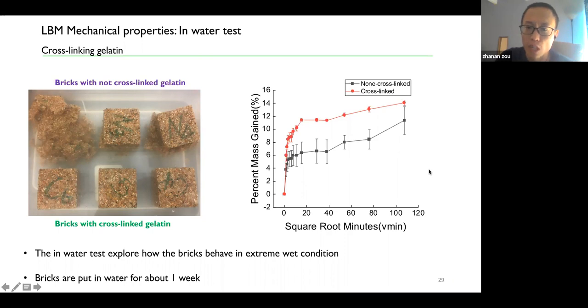So we observed that even if we cross-link the gelatin, it's still absorbing a lot of mass from the water, and this is because cross-linking the gelatin only stabilizes the polymer network, but it doesn't necessarily change the hydrophilicity, or in other words, it won't flip it from hydrophilic to hydrophobic.